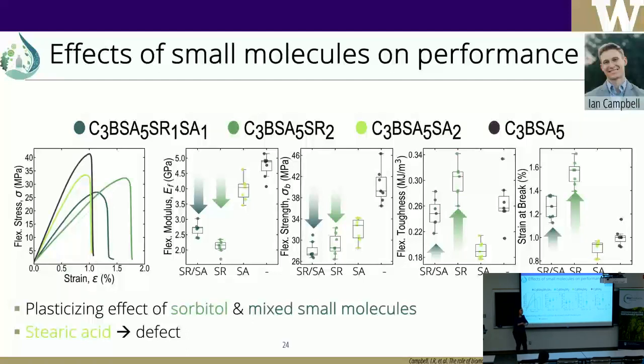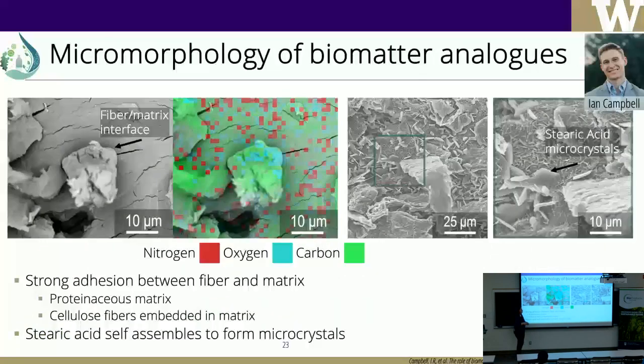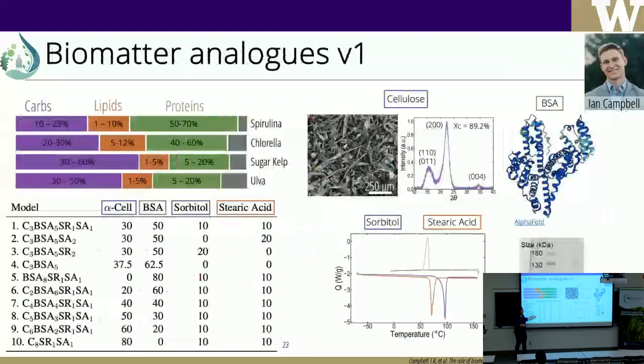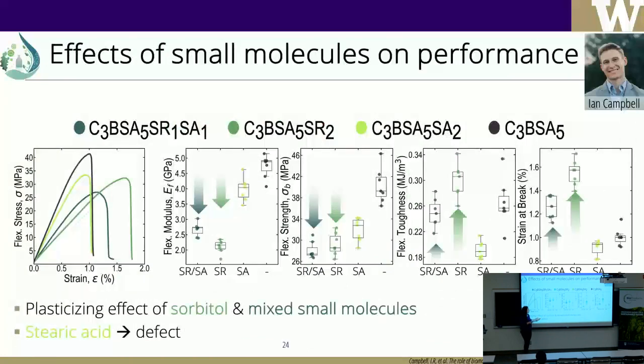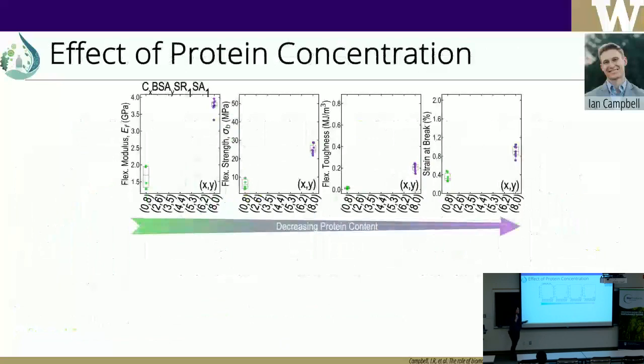And that now starts making sense if we think about the picture that we saw before, because those crystals are strong, but they're not as strong as cellulose. And the fact that they migrate all the way to the surface tells us that they would likely act as a defect, and that is what we actually see over here. They function as a defect where they are reducing all the properties in our composite. So the first round of understanding kind of makes sense.